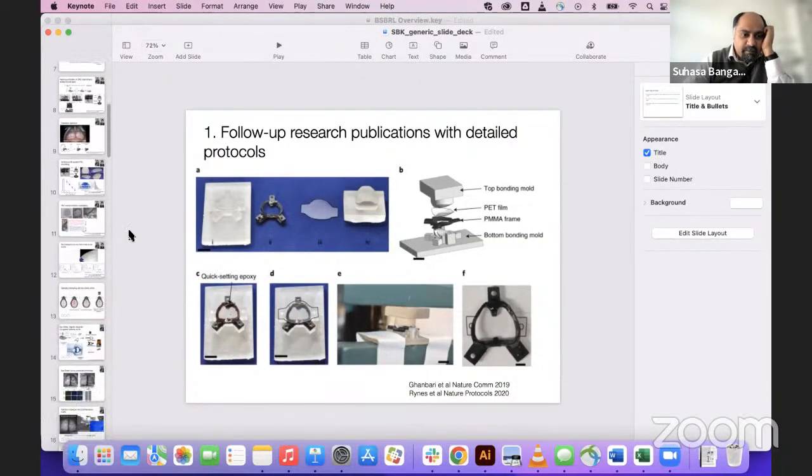No, but in the paper, we do point spread function analysis as compared to a glass cover slip. Because these films are thinner than the usual cover slips that most imaging objectives are designed for, which is 170 micrometers or so, you will see some decrease in the optical imaging performance. But we're able to see structures as small as dendrites when we do structural imaging on Thy1-GFP mice.